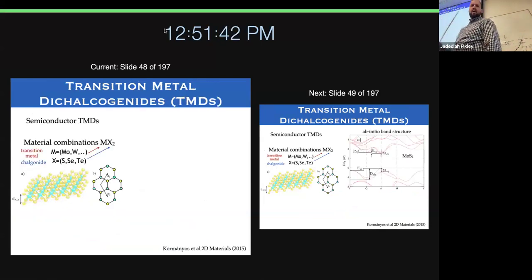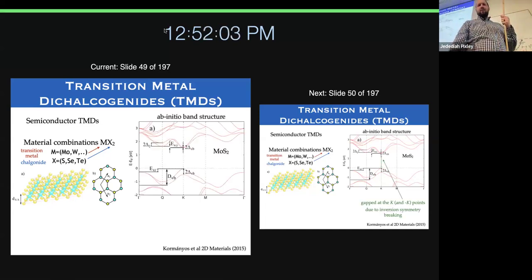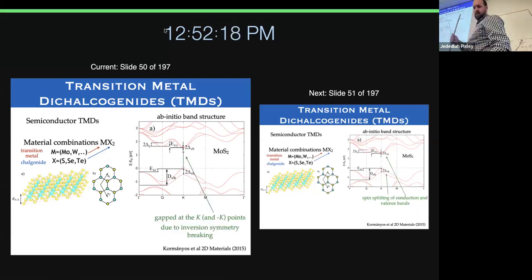Set the stage. So TMDs, transition metal dichalcogenides, basically you have a transition metal and two chalcogen atoms. And if you look at this, you have a 3-layer thick material now, but if you think of a bird's eye view, it's a honeycomb lattice where you strongly break the AB sublattice symmetry because they're two different atoms sitting there, okay? But they're even richer than just breaking the sublattice symmetry because they have a large Ising spin-orbit coupling. So these are weakly correlated materials. You can do ab initio with rather high accuracy. What you're seeing here is a very large band gap due to the AB sublattice symmetry breaking. This is breaking inversion.